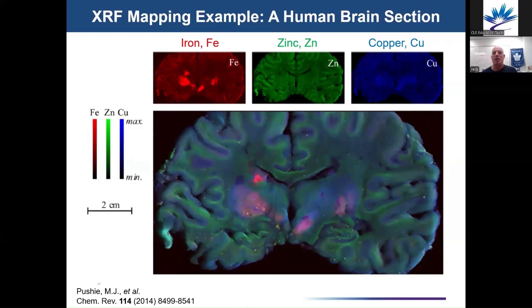Here's an example of a post-mortem section of a human brain. And this was taken from a person who was suffering from multiple sclerosis, or MS. An iron accumulation in the brain has been observed in MS patients, and it's believed to be associated with inflammation and vascular abnormalities in the brain. The small maps here illustrate iron and zinc and copper in this brain section, while the large map combines all three elements. And you can see very intense hotspots with significant iron accumulation in this brain section. And the zinc and the copper, they're much more evenly distributed throughout the brain.